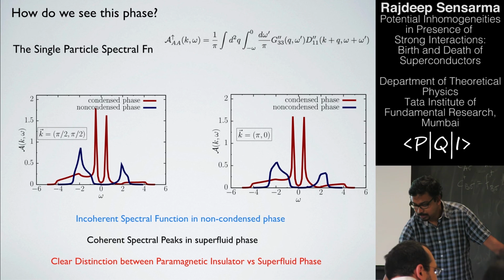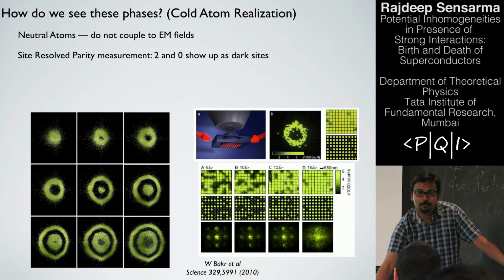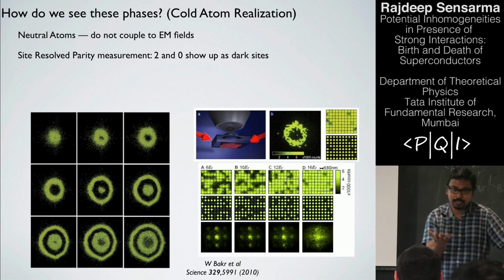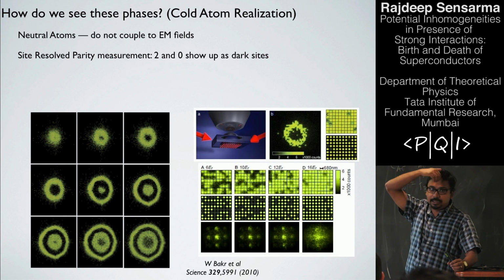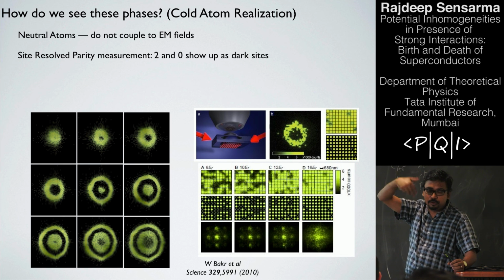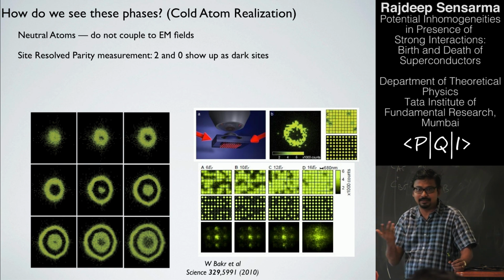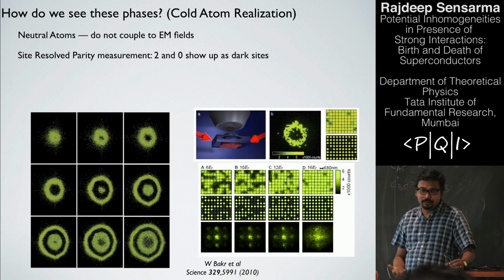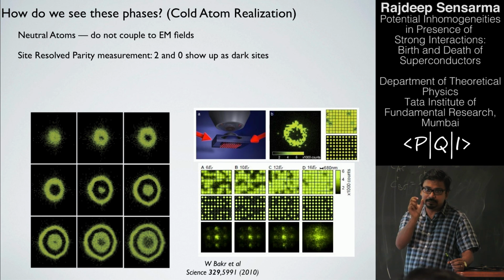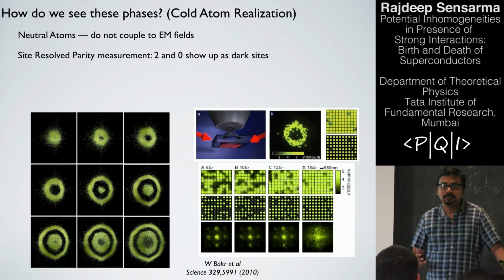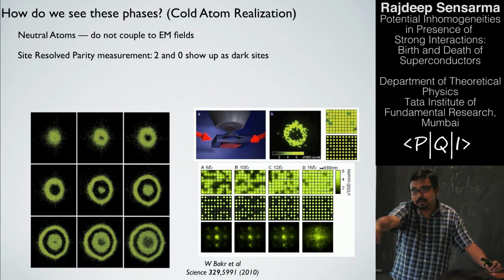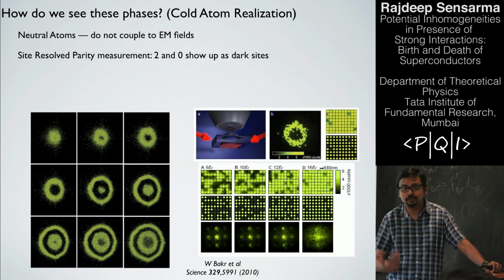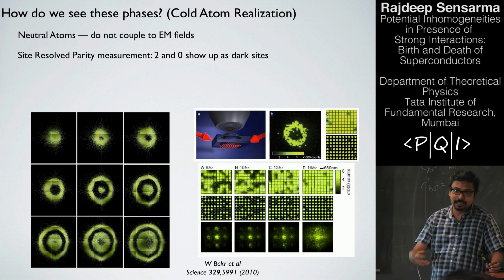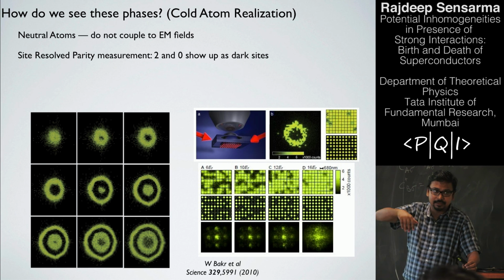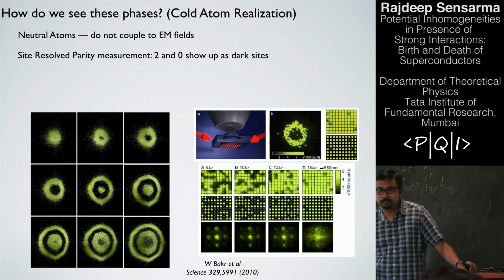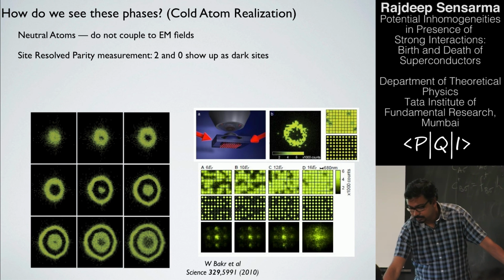So the other way of thinking about it, a very cold atomish way, is that people can make these parity measurements locally. So a doublon is a 2 and a holon is a 0, which both show up as, I guess, black, and the single sites show up as bright. If you are in the paramagnetic insulator phase, whenever you get dark sites, you should get them in pairs. In the superconducting phase, single 2s and 0s proliferate, so you should see more single dark sites with no other dark sites on neighboring sites. So the statistics would start changing in this way.